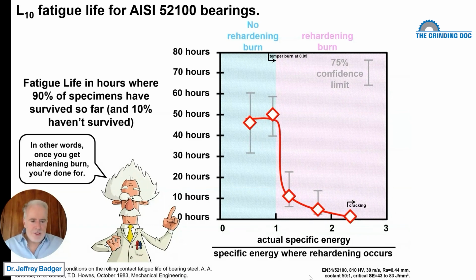And then if he really pushed it too far, where he was grinding at way too high temperatures, then he got cracking of the material. And if you crack your material, well, you're not going to get much of a fatigue life.